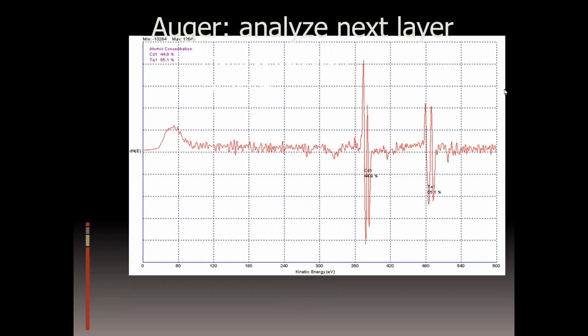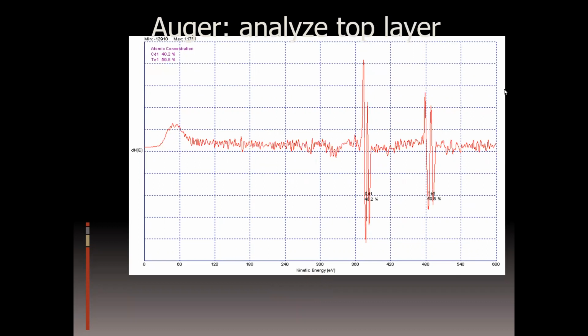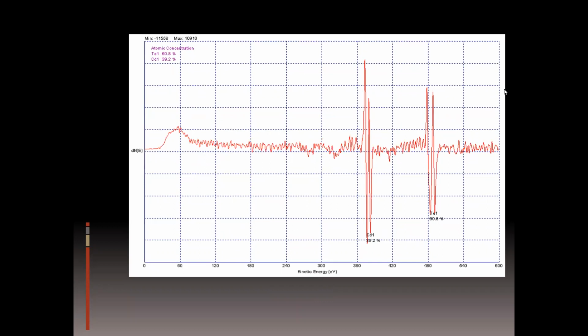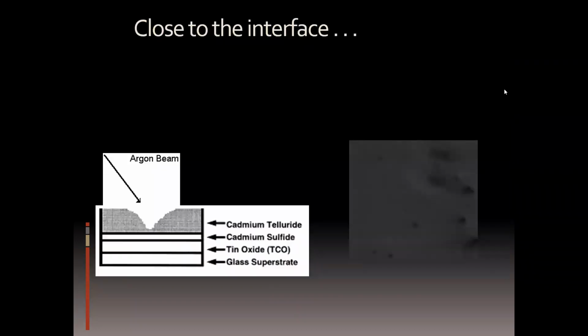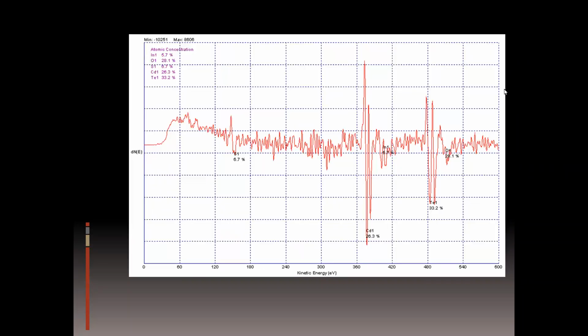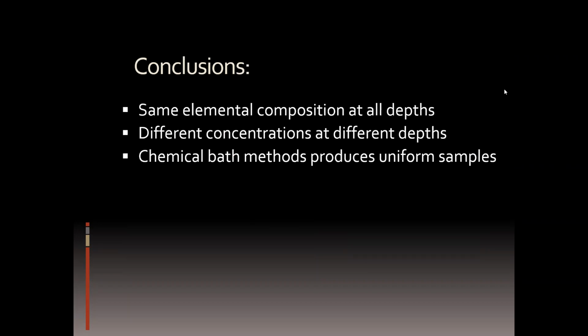This is the next layer. Next layer. Next layer. Next one. And we got all the way to the interface, and still the same. So, conclusion, nothing happens. It's basically a well-mixed material, and the method that you're using for creating it is working. And that was the observation: the same elemental composition at all depths. We found slightly different concentrations at different depths, but taking all of this into account, the chemical bath method produces more or less uniform samples. So that was the conclusion.